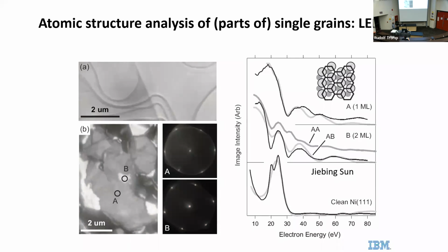And here we have choices. We can put the carbon atoms either on top of a nickel atom or in a hollow. It turns out they sit on top of the nickel atom. That's the comparison here. And then we have two layers of graphene. You can shift them either exactly on top of one another, right? So the two chicken meshes fit exactly on top of one another. Or you can shift them so that the second graphene atom sits on the hole of the first graphene atom. It's called AB. And it turns out that it likes to form this AB stacking, right?